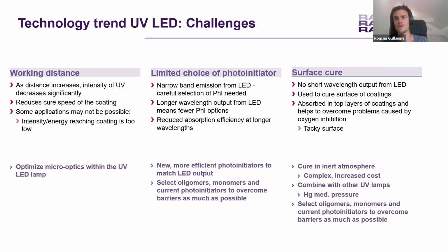And again, because of the wavelengths of the LED in the UVA, we can have some challenge on the surface cure. When we need a very hard, scratch resistant, closed surface, it's more complicated with LED because we don't have the UVC, which is perfect in order to cure the surface of the coating. That's another challenge. We can also face some tacky surface, because with the LED, we cure very well in depth because of the UVA. The UVA is able to go deeply into the coating quite easily. So with the LED, we have no issue curing in the depth of the coating, but the surface of the coating is a big challenge. Again, the main reason is the wavelengths available with the LEDs.